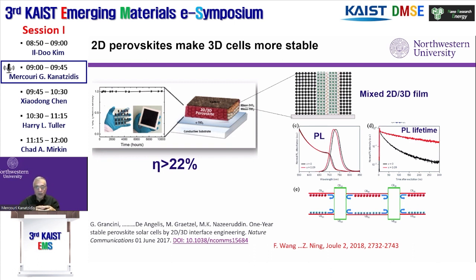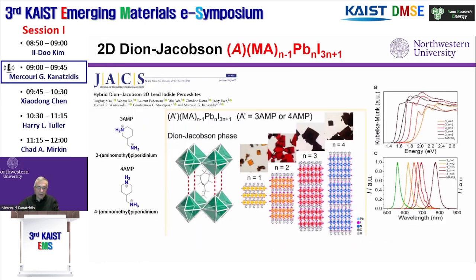This is remarkable. And not only that, the proximity of the 2D to a 3D grain also made the 3D a better semiconductor, as shown here in the lifetime of the photoluminescence of the 3D. When there is zero 2D in there, we have a faster decay, but when you have some 2D next to it, we have a longer decay. So there's some passivation also possible in the 3D perovskites. So now, most of the papers have this 2D-3D mixture in the device. These are the Ruddlesden-Popper, and this is another very interesting family.